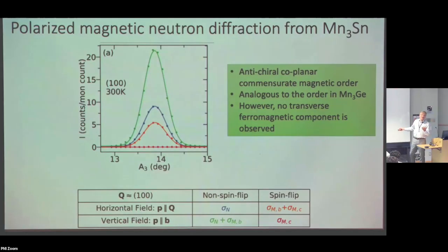parts of the cross-section. And so I can either have a process that flips the neutron spin, or I can have a process that doesn't flip the neutron spin, and I keep track of the intensity in each of those channels. I measure them separately. I have to spend time measuring the one, then the other. And for example, the non-spin flip channel with the neutron polarized along the wave vector transfer has only nuclear intensity in it. That's the blue one, so that is the nuclear intensity in this peak. It's as much as this blue point here.